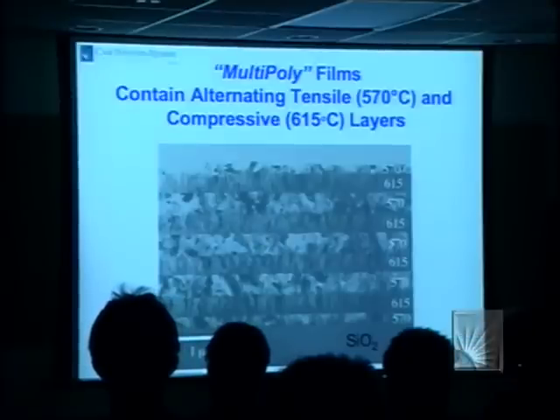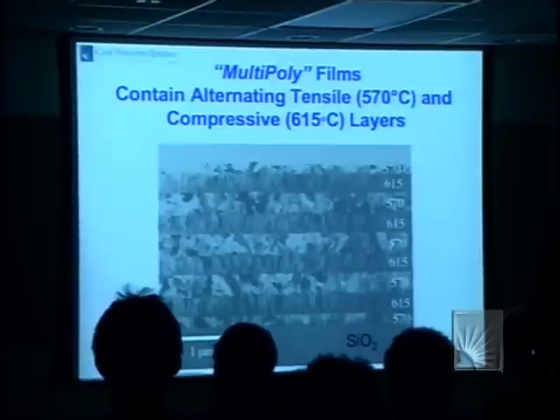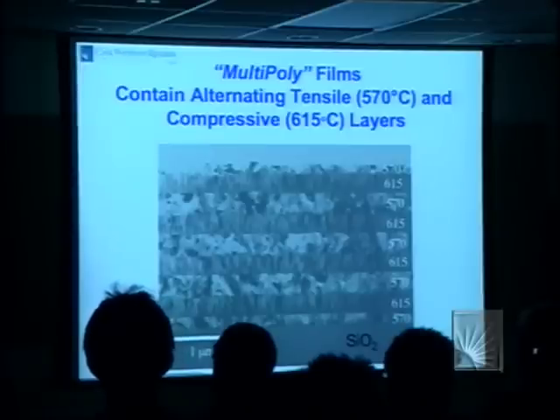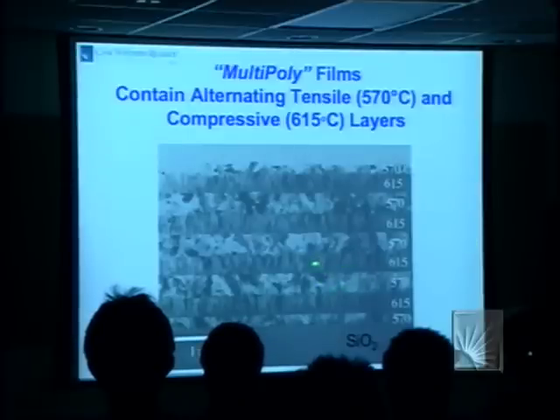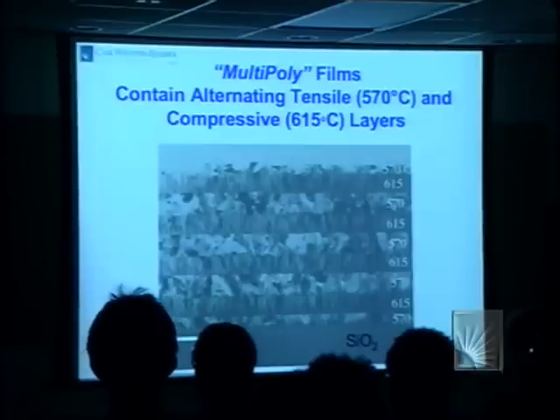As I mentioned earlier, the kinetics of deposition are sufficiently rapid at this temperature that the atoms are not able to, by surface diffusion, when they get deposited from the vapor phase onto the pre-existing columnar silicon, move around until they find the correct equilibrium position to allow these columns to grow. And so this 570 film is amorphous and doesn't crystallize till you deposit this 615 and so on. And the final film was deposited at 570 and is then annealed at 615 to crystallize the last bit of material. And in principle, this gives a way to control the stresses in the film.